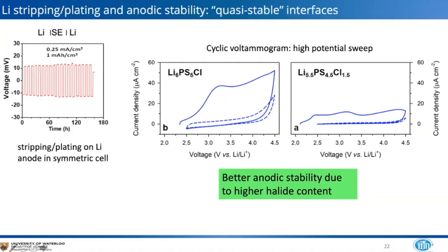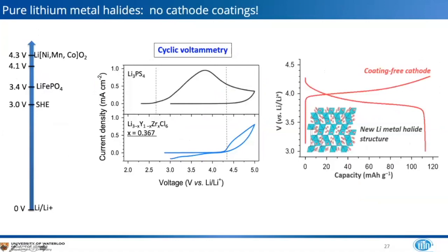And when we examine this material using CV, we could see that there was much less current passed for the chlorine-rich versus the pristine argyrodite material, especially after this is the first cycle and this is the second cycle. So you can see that we're forming a passivating layer, and we have better anodic stability due to this higher halide content. And so that inspired us to look at pure halide materials.